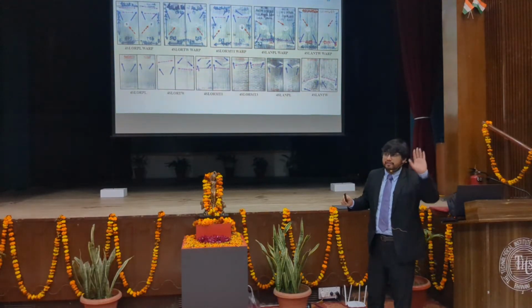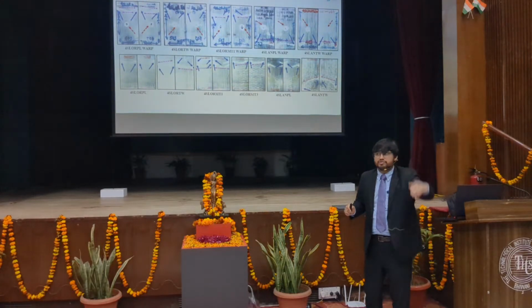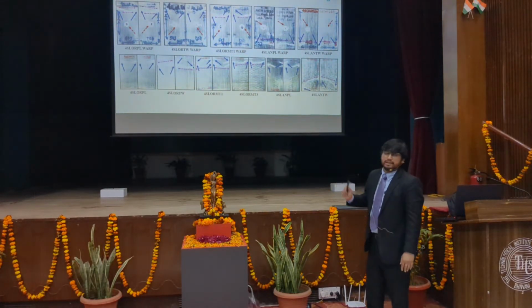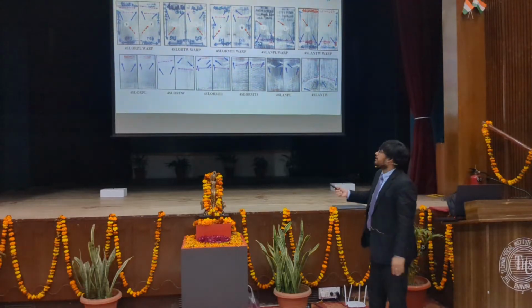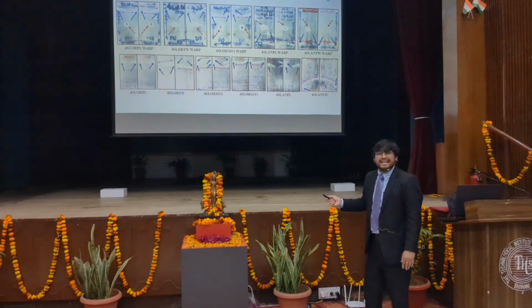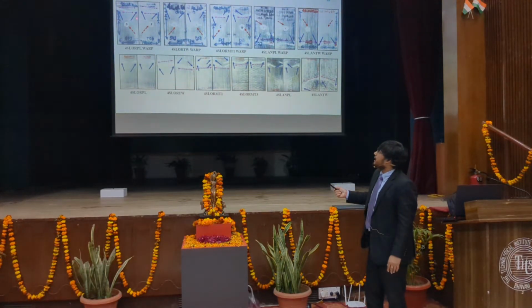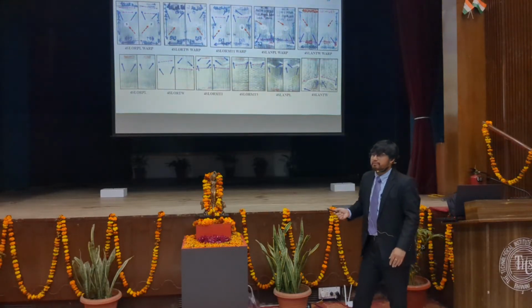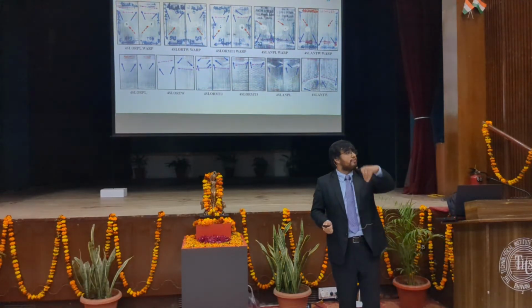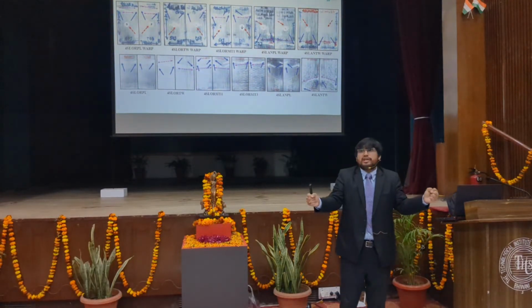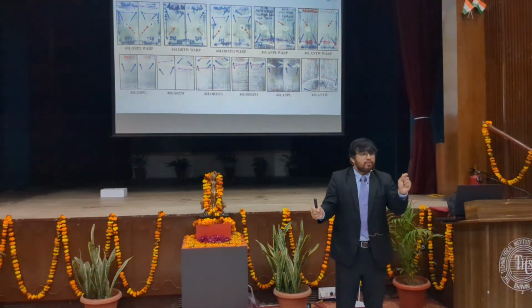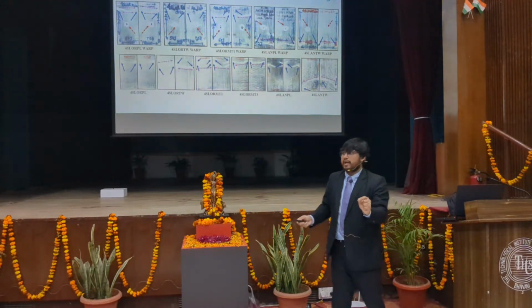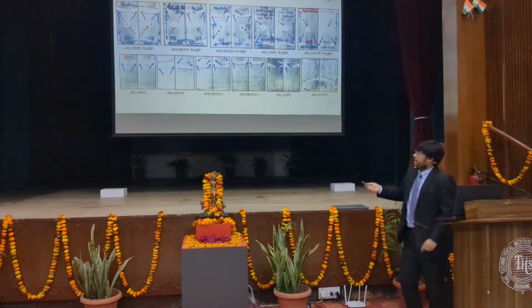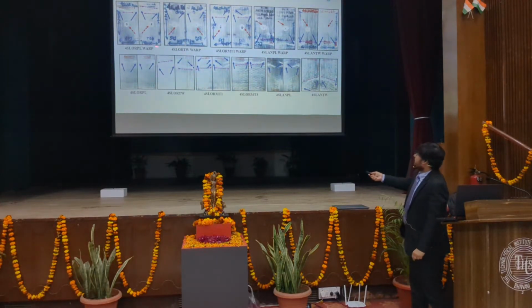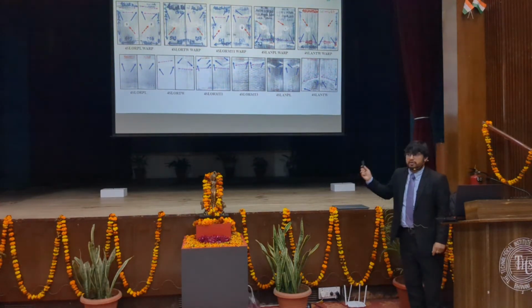I tried to wait till the 50% deflection of the maximum stress, but nothing happened actually. So what I interpreted from these structures is that either some sort of slippage happened due to the lower thickness, or my binding yarn prevented the crack from moving from the top to the bottom. So my structure was able to withstand, even though it was perforated in a very significant way in the middle. And it happened even for the non-impacted material, you see. It's quite identical, impacted and non-impacted structure.